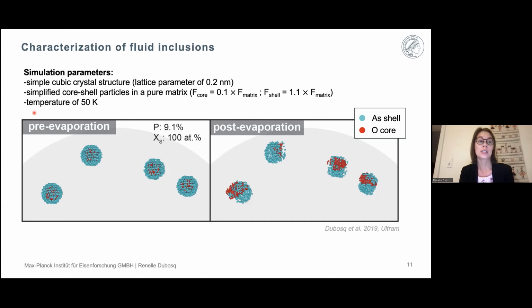And the fluid inclusions here were simplified to core-shell particles in a pure matrix. The core particles were to represent loosely bonded particles or atoms that form a fluid. So for this case, they were assumed to have a significantly lower evaporation field, 10% that of the matrix. And the shell here was assumed to be a mix of both shell atoms and matrix atoms, where the shell atoms had a slightly higher evaporation field than the matrix. Here the shell atoms are assumed to be arsenic, which form the coating of the fluid inclusions.